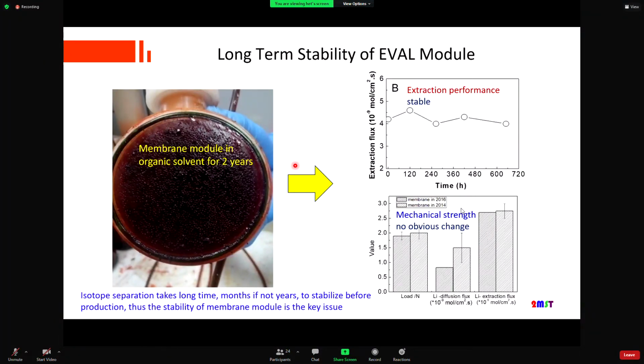in touch with the organic extraction is really critical. We put the module into the system, in contact with the organic extraction for 2 years, and we take the samples out. You will see the extraction of lithium is very stable. This gives us some indication that the membrane performance is stable.